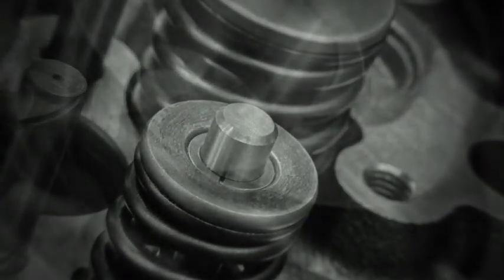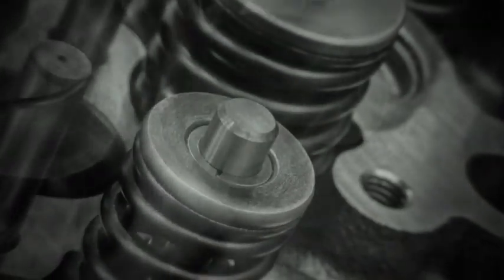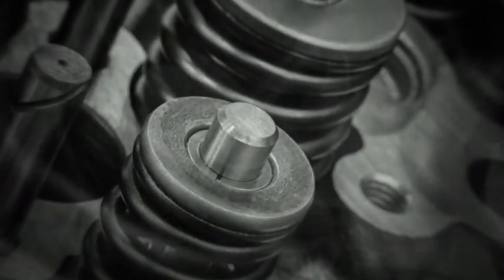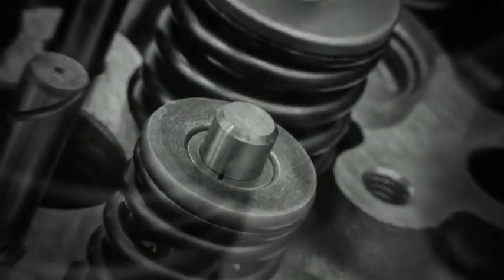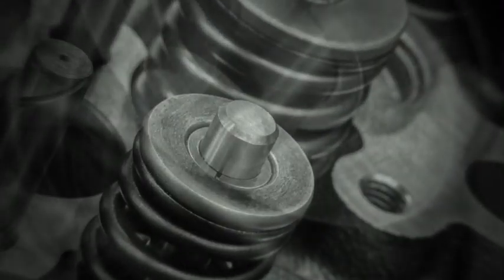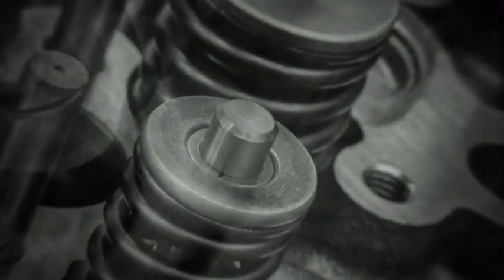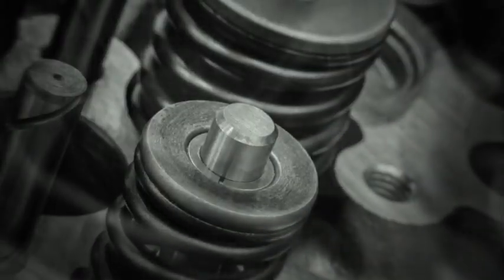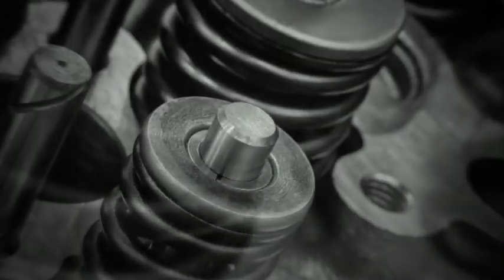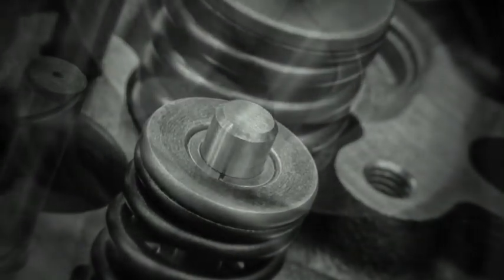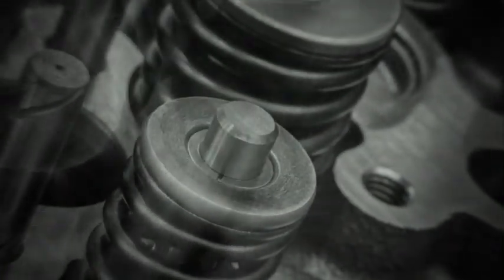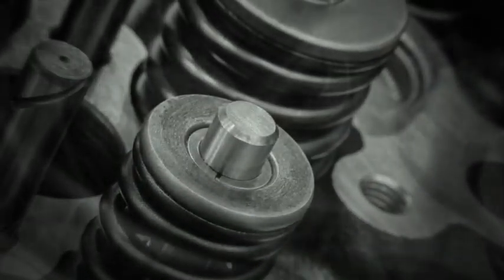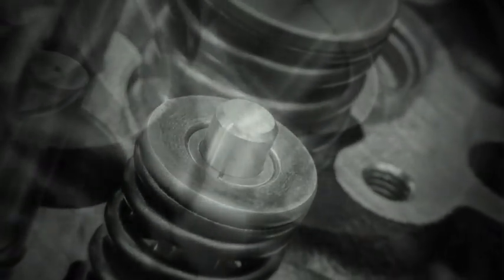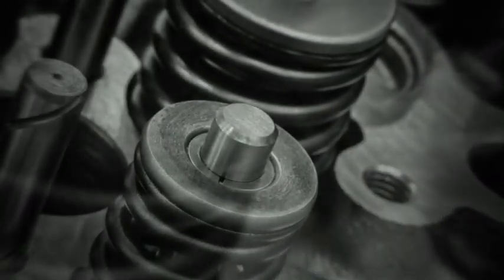A spring cycling between two compressed positions experiences a mean stress and an alternating stress. Preload can raise the mean while reducing the chance of separation. The acceptable combination depends on material, surface, life target, and reliability. A spring used only a few times can operate nearer its static limit than one expected to cycle continuously for years. Corrosion fatigue is especially destructive.